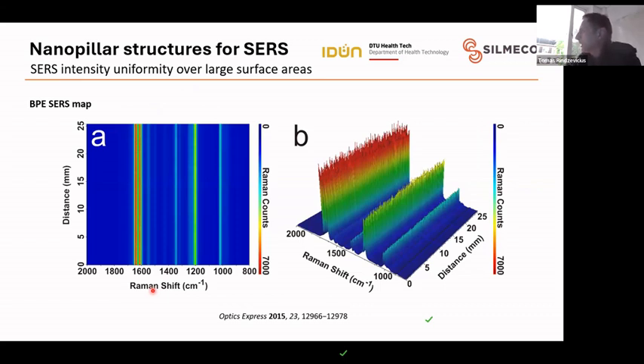And so then, one property that I mentioned previously: the uniformity. So what does uniformity mean? Well, again, when we have a surface and we measure at different points on the surface, the question is how similar is our measurement? And we noticed that if you really carefully fabricate silicon nanopillars, you can get quite a uniform, reproducible signal. It is difficult to do, but it is possible. So here, for example, on a 25 millimeter area, like a line scan, you can see that the signals are quite good. And I believe this was 10 or 100 micromolar BPE molecule.